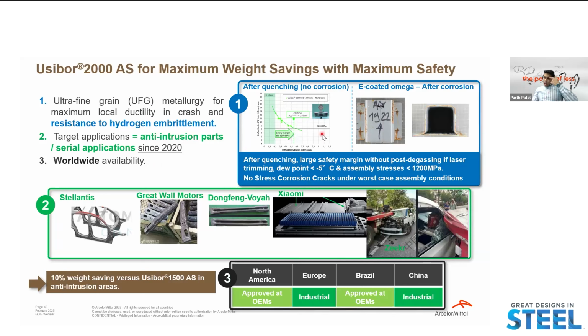Again, looking at this chart, after quenching in hot stamping, you heat it in the oven to 900 degrees Celsius. You're going to have some absorption of hydrogen at the hot stamper, typically 0.2 to 0.3 ppm diffusible hydrogen in industry.